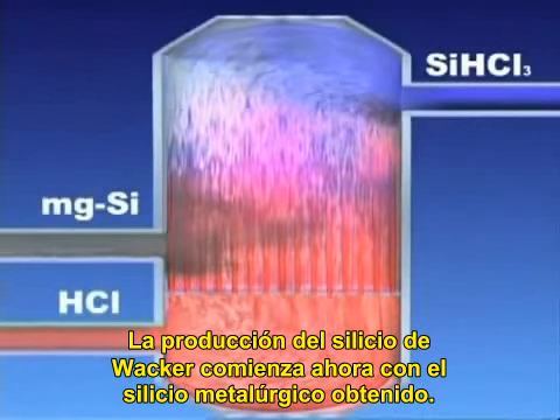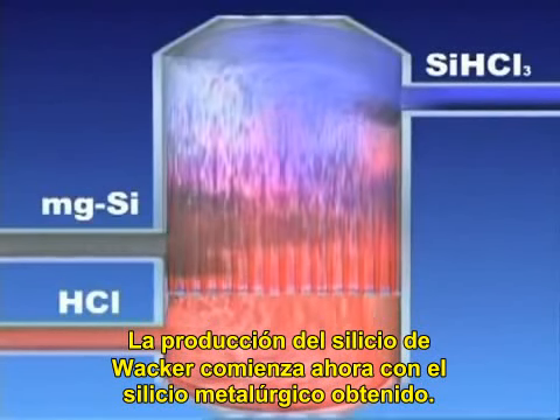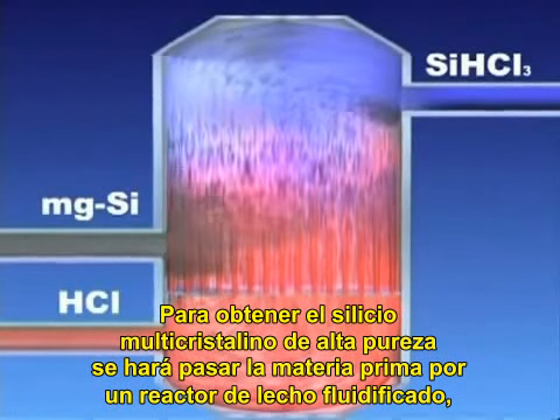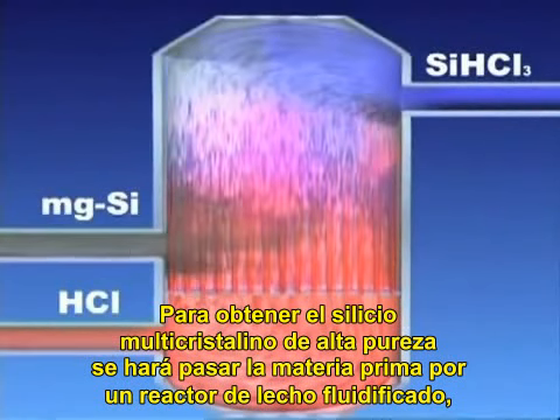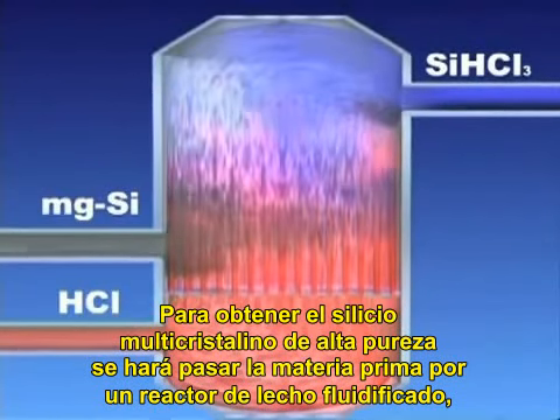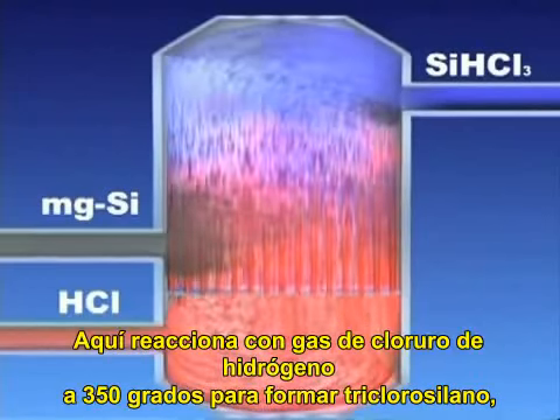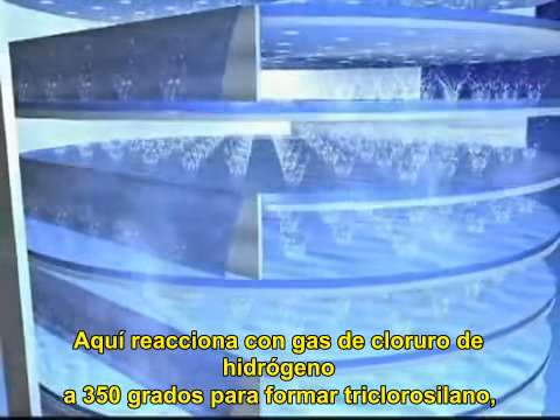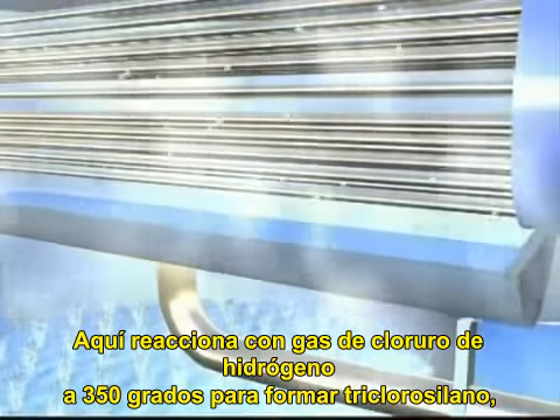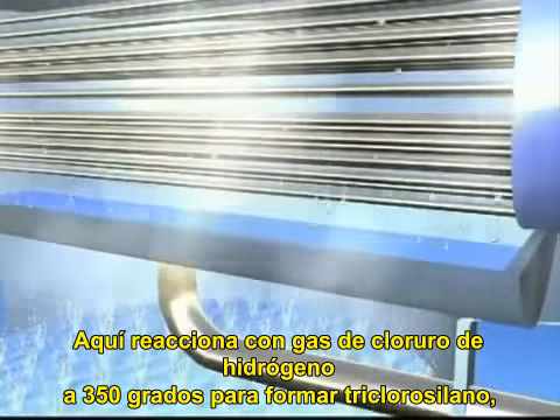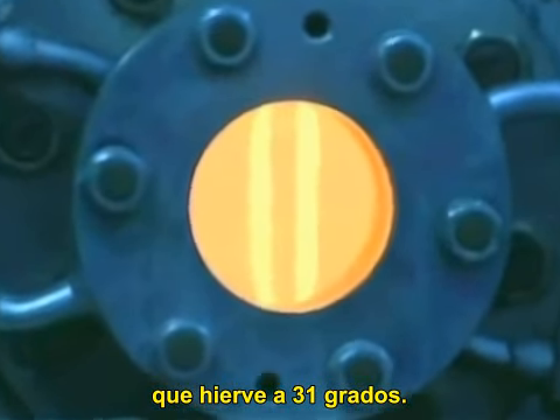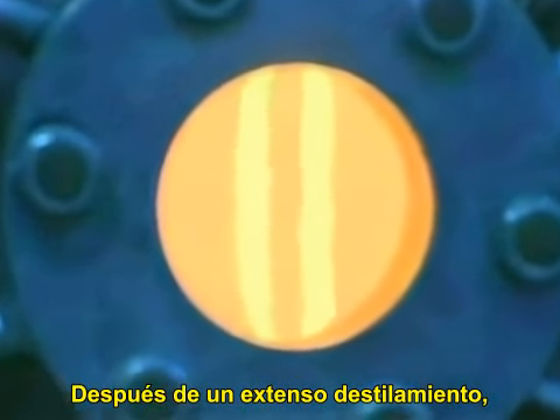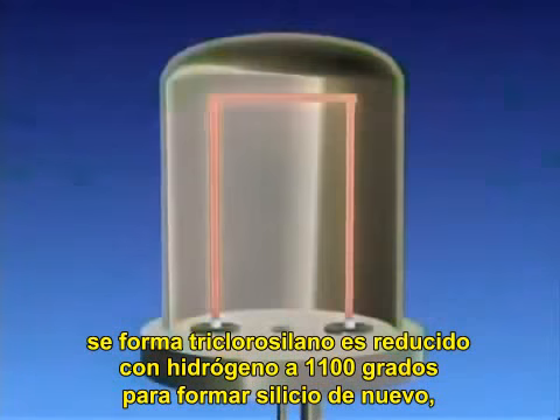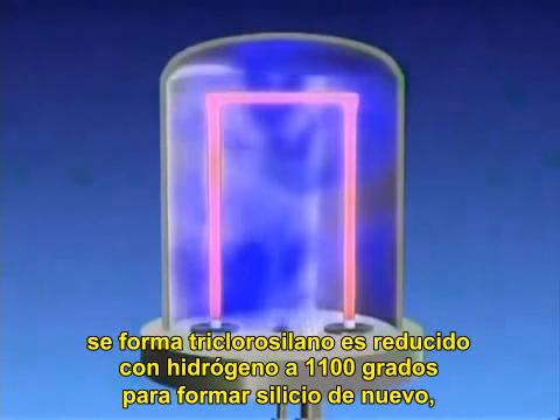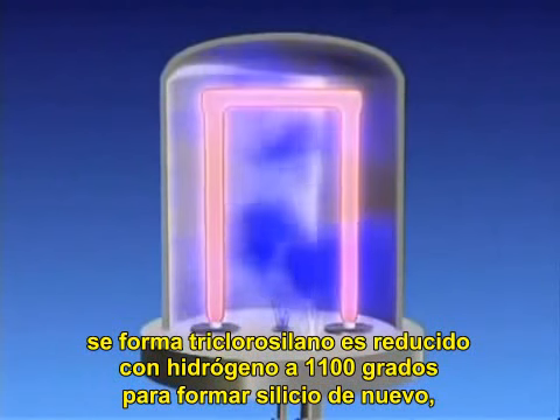Wacker's polysilicon production starts with metallurgical silicon. The first step in refining this raw material to hyperpure multicrystalline silicon is a fluidized bed reactor. Here, the silicon reacts with gaseous hydrogen chloride at about 350 degrees centigrade to form trichlorosilane, a liquid that boils at 31 degrees centigrade. After extensive distillation steps, the now hyperpure trichlorosilane is reduced by hydrogen at around 1100 degrees